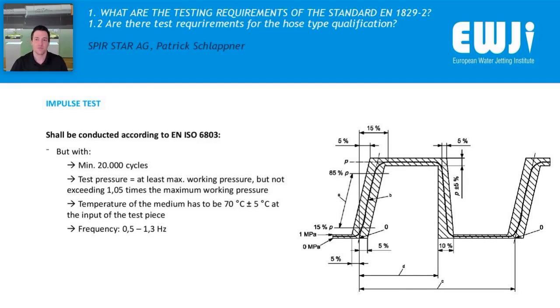Another test is the impulse test. This test is conducted according to EN ISO 6803. But based on the EN 1829-2, the hose has to reach a minimum of 20,000 cycles. The test pressure has to be at least the maximum working pressure. And the temperature of the medium has to be 70 degrees Celsius. The frequency is between 0.5 and 1.3 Hertz. On the right, you can find a typical pressure test curve.